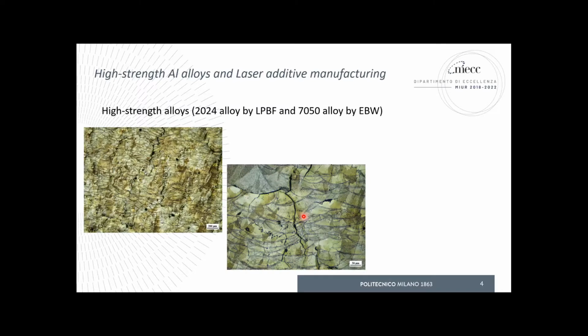If we move to high-strength alloys, then lots of trouble come around. This is, for instance, 2024 aluminum alloy, an aluminum, copper, magnesium alloy, but the same holds for 7000 series alloys and for some 6000 series alloys. You can see again the same kind of melt pools, but this time very often you can see cracks that are running usually intergranularly along the columnar grains. So it's really a disaster when you go for laser additive manufacturing of very high-strength aluminum alloys. Originally there was a kind of gap in the palette of the materials available for the manufacturing of demanding parts for the aerospace, for the motorsport, for many applications.